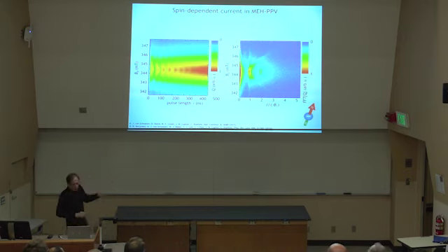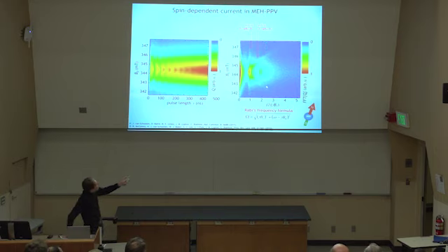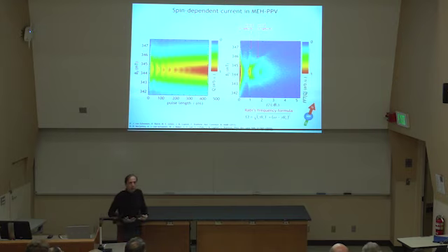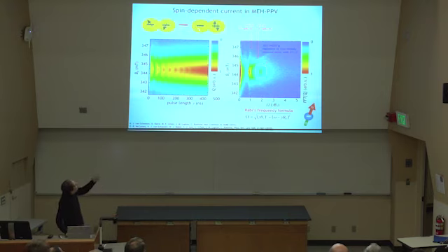What we also see, the other features, so this one here, this is a hyperbolic function that's well described by Rabi's frequency formula. So we learned something about the distribution of local hyperfine fields that these paramagnetic states that produce this reflect equally to the vertical line. And so there's lots and lots of information that we can get out of this. We can now model our Hamiltonian, and this particular effect that you see here is indeed the Pauli spin blockade that I talked about earlier.